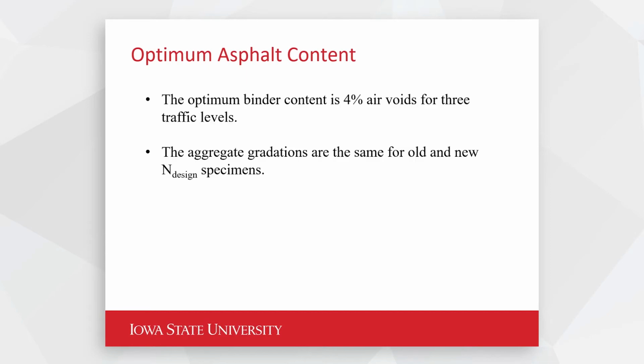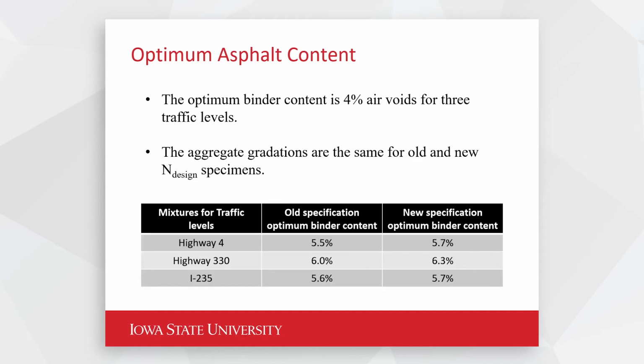So again, we're using compaction criteria of designing a 4% air void. So what happened was we reduced the number of compaction effort. And then if you page down, you can see how overall, with the old design, as an example on Highway 4, the optimum design was 5.5, with the new was 5.7. And so overall, the three different mixes, we did see an increase in the asphalt content. Not quite as much as we had anticipated. We would have thought it had been more like in the order of 0.4% or thereabouts. But nonetheless, we did see an overall increase in the binder content.